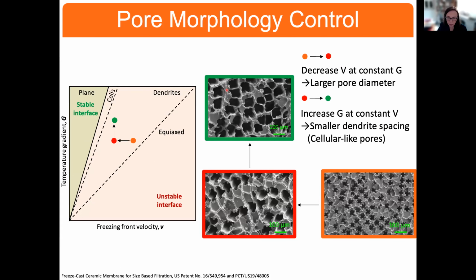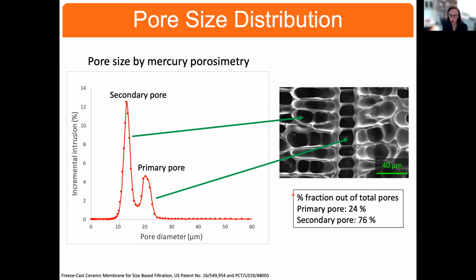Okay, so this is what we're doing. Here's our microstructure map again that shows us that if we start here and increase the temperature gradient, one of the things that you see is that we have much smaller dendrite spacing. They're much closer together, so these are moving toward cellular-like pores. If we start over here at a high freezing front velocity and decrease it, we end up, as shown earlier, with much larger pore diameters. Okay, so these are the knobs then that we have to turn.